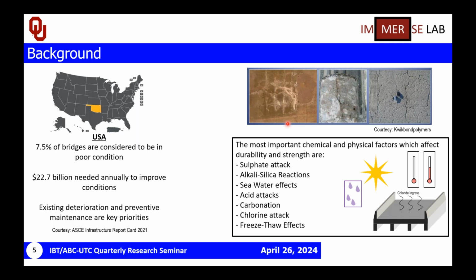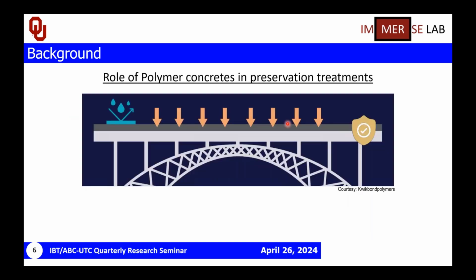What are the roles of polymer concretes in preservation treatments? If you look at the bridge deck, for example, bridge deck overlays. When polymer concretes are used as bridge deck overlays, they minimize penetration of water, oxygen, chlorides, and de-icing salts. They act as a protective barrier on top of the concrete bridge decks. And also they improve deck performance life and service life of the bridges overall, but the deck itself can be improved and the life can be improved.